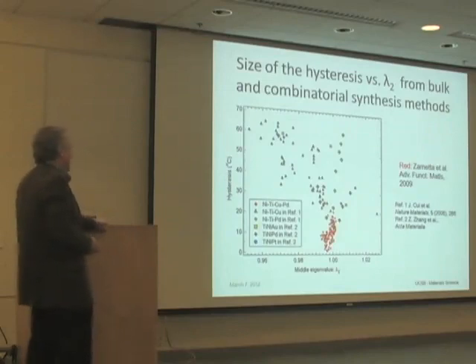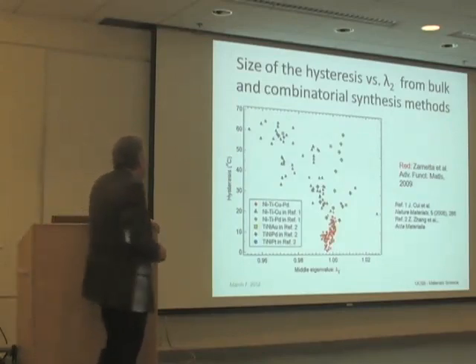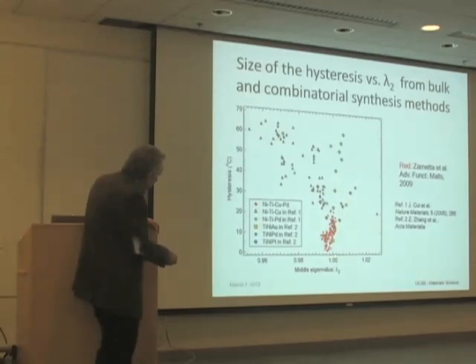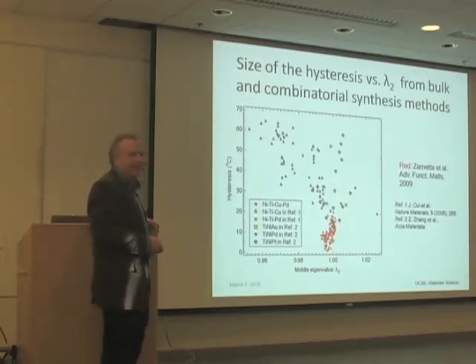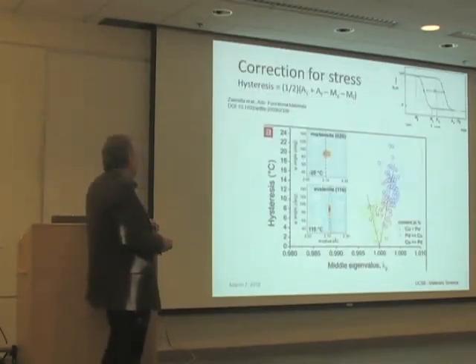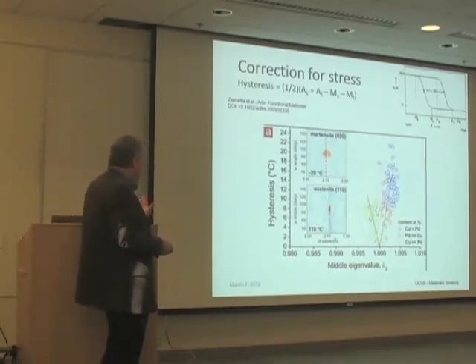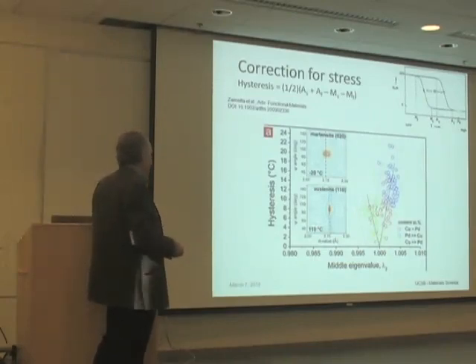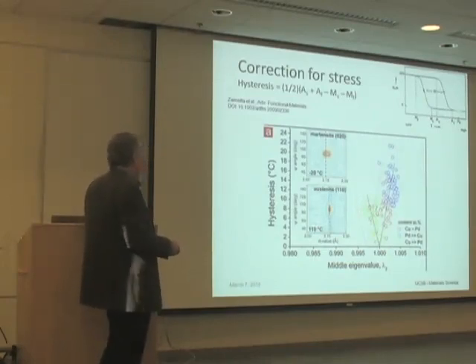You also notice that the minimum of this graph is not at 1. It's displaced slightly to the left of 1. In fact, they realized that there was stress in the films when they were doing these measurements. There's a measurement of that stress here and an accounting for that stress. I'm not sure I buy everything that was done here, and I didn't do this. But anyway, the end result was this graph, which was minimized here, moved over to there.